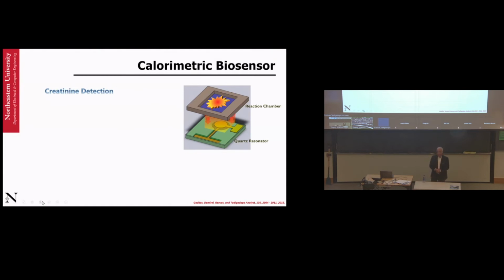Or it'll just damp. So why not use the capability of heating it up through a very small gap, because it absorbs the radiation that comes out. And so, well, just keep a reactor only 100 microns away, maybe 50 microns away. So it's not mass loading, but you do your reaction there, use the enthalpy of heat, and actually let it couple straight into the resonator. And then you suddenly have a biosensor. But not only do you have a biosensor, you actually have a disposable biosensor, whereby you can use this top part where I have this schematic with the little explosion going on. You can throw it away after you're done, which means that you can actually use it for doing proper biomedical testing if you want to.